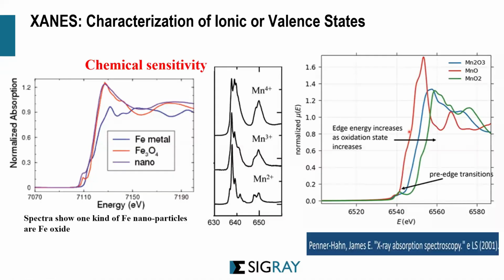The same thing applies to manganese. In this case, you see that as the manganese goes from 2 plus to 4 plus, the curve starts to shift towards the right. You can also see the pre-edge in that transition, all of which will tell you very specific information about the two.